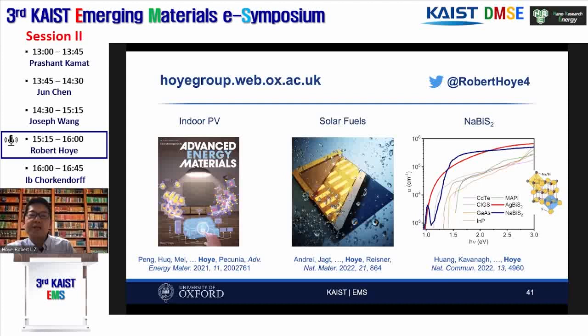So for example, this would inform us that we need to find compounds which have stable valence s2 electrons, which can hybridize with anions in a very similar way to what you find in the perovskites. And of course, more recently, other design rules have been developed, such as those based off crystal structure and lattice parameter, which help us to refine the search.